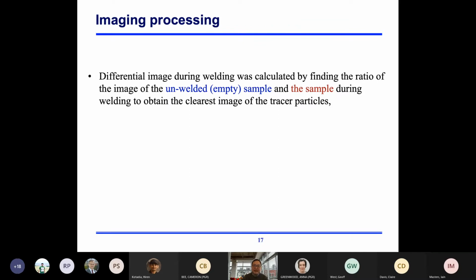Image processing is another aspect. After doing the experiment, processing the image is important. First, we use a differential imaging method. We run an experiment without welding and with welding, and then take the differential signal from each other, which will give you the phenomena that happen inside the area you are interested in, for example, when you want to see the signal within the melt pool.